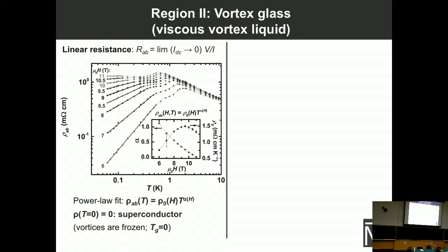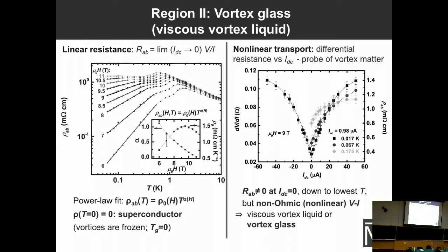Then we also studied, as I said, nonlinear transport. In this regime, here is an example of what the data look like. This is the differential resistance as a function of DC current at 2 different polarities and 3 low temperatures. You can see, for example, at 17 millikelvin, these are the black symbols, the resistance is still finite at the zero DC current limit. However, the voltage-current characteristic is strongly non-ohmic, which is what one expects in the viscous vortex liquid that we are calling, for convenience, vortex glass.